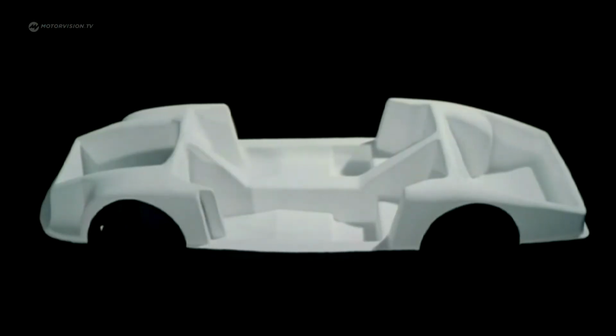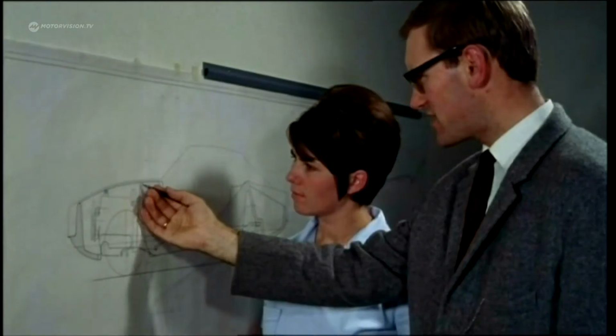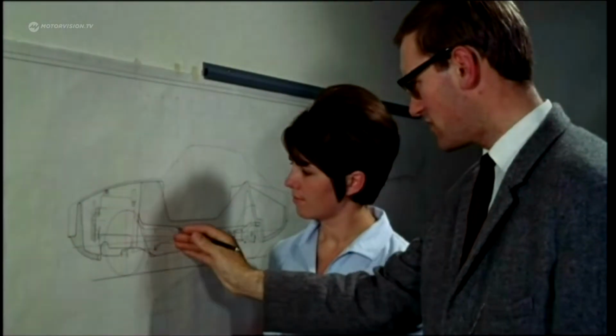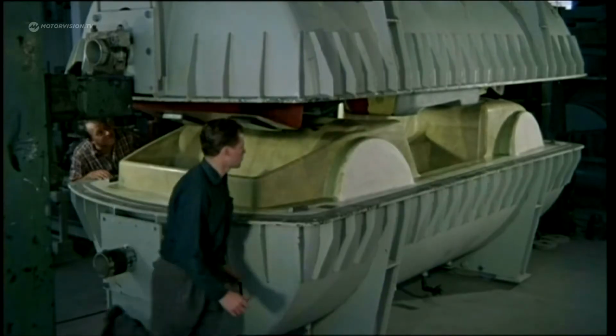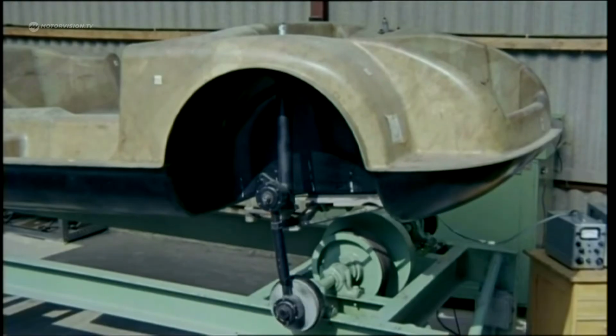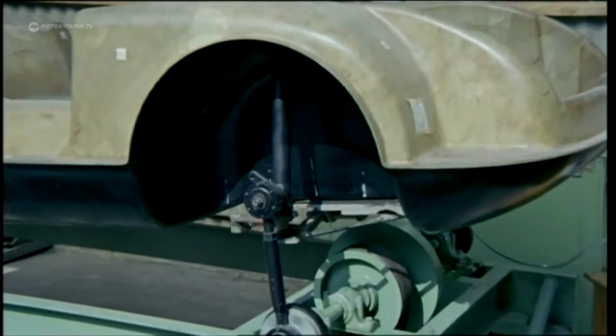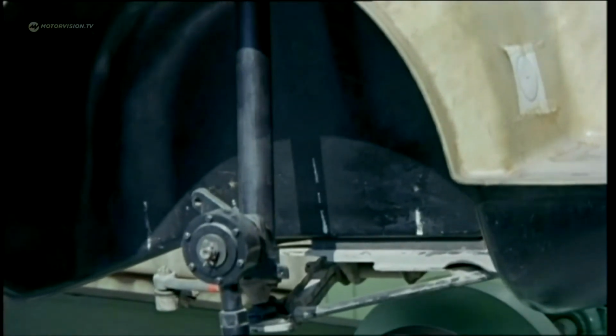The big feature, even the chassis is made of a polyurethane sandwich shell without any metal reinforcement. There were cars in plastic construction before, but they usually had a frame made of steel tubes. The chassis of the K67 still appears to be stable enough. After more than 6 million load cycles, no changes show up on this test body specimen. The dynamic fatigue tests confirm the high strength of the self-supporting floor plan reinforced with fiberglass plastic.